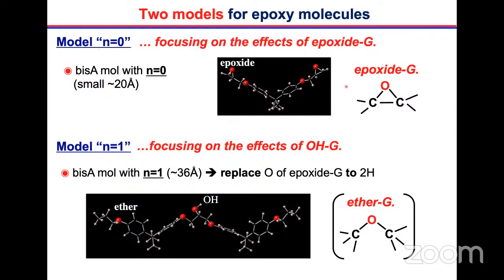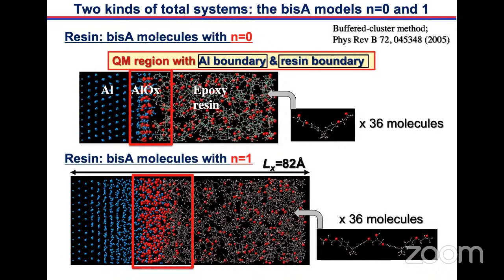For the n equals 0 model, we focus on the reactive groups. Still, the epoxy group exists at the two ends. For the n equals 1 model, we focus on the hydroxyl group here, and the two epoxy groups are replaced by CH3. We use such two models to produce the interface. In the n equals 0 case, we have the aluminum here, the surface aluminum oxide, and the epoxy resin. The epoxy resin is produced by 36 epoxy molecules entangled.